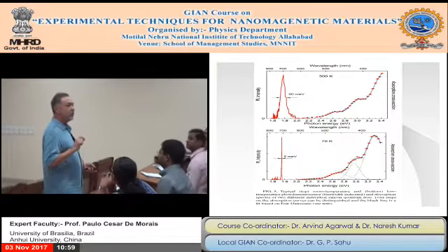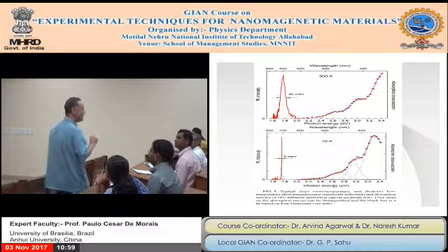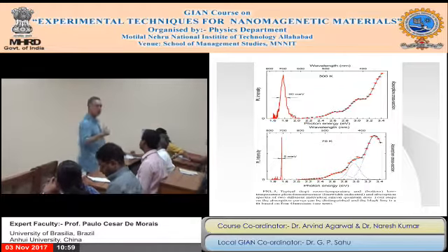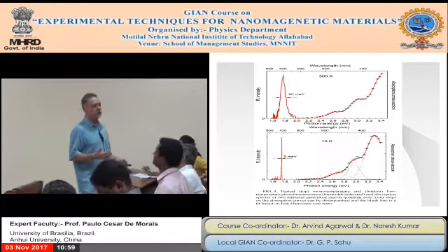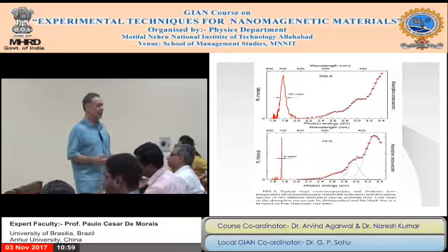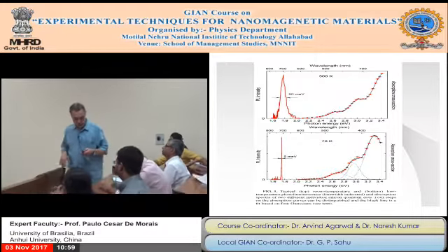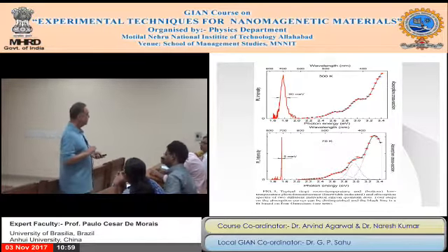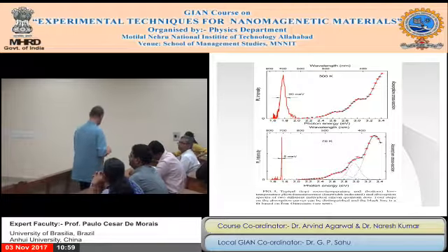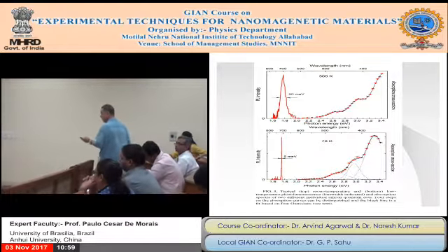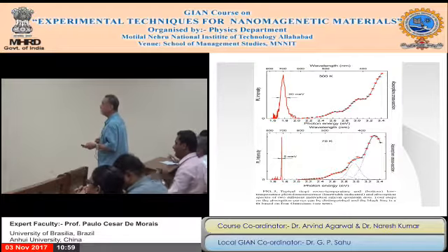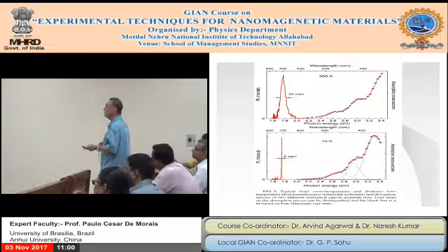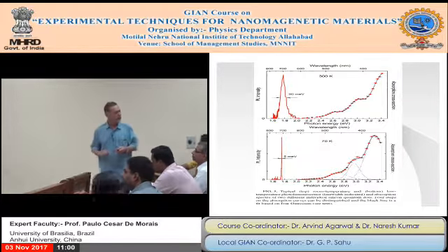But remember, yesterday I mentioned to you, don't do this with Raman spectroscopy. For Raman spectroscopy, you better perform it at room temperature. Okay? It's no cost. But for luminescence, you better lower the temperature. The lower you go, the higher the signal, and the better the resolution. But this is typical. In this paper, they calculate the absorption band, and you can see the solid line is the calculation. Very good.